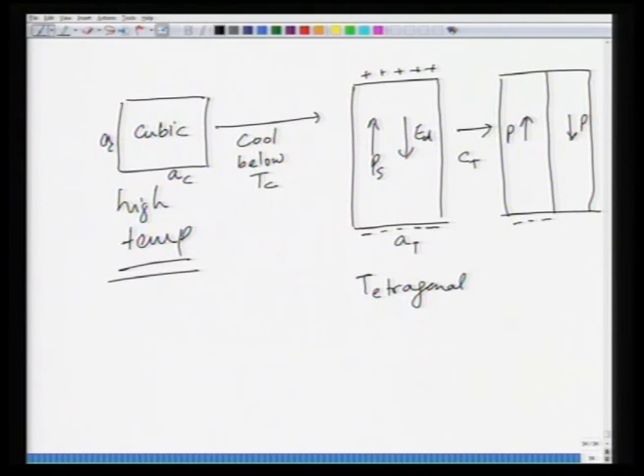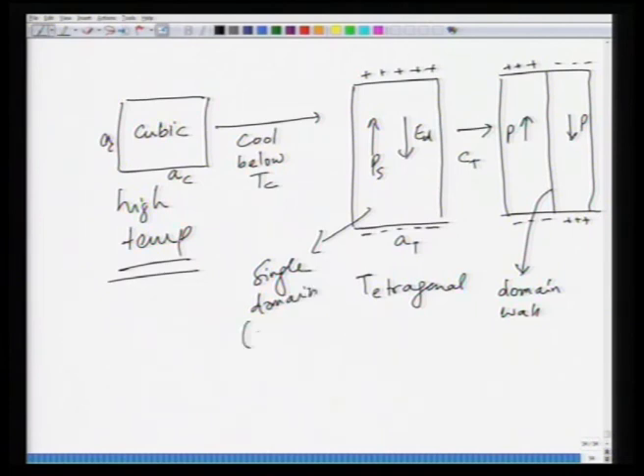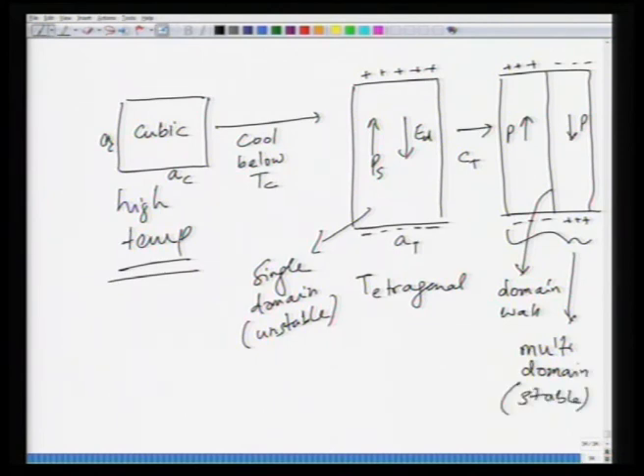So here, the surface charge density goes down. As a result, you can see that the depolarizing field has disappeared, and this kind of domain boundary, this wall, is called a domain wall. So this was single domain, unstable, and this state is basically multi-domain, which is a stable configuration.